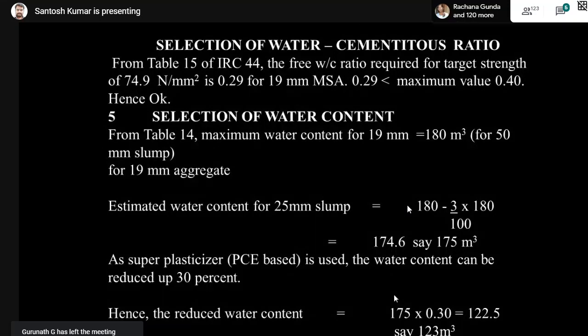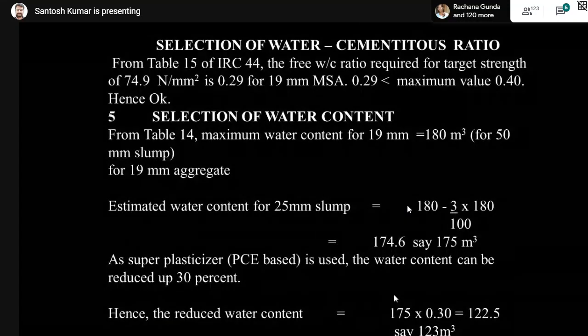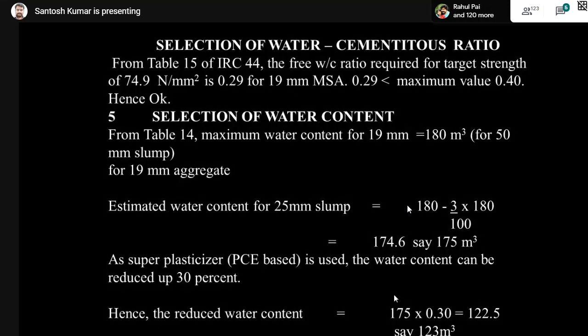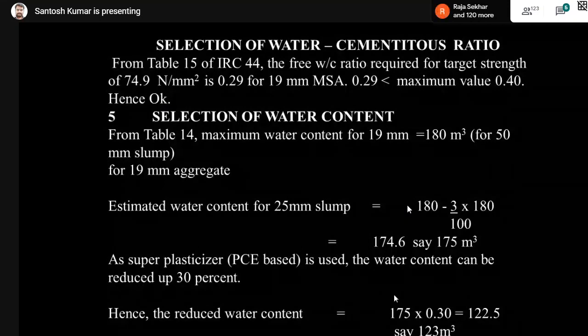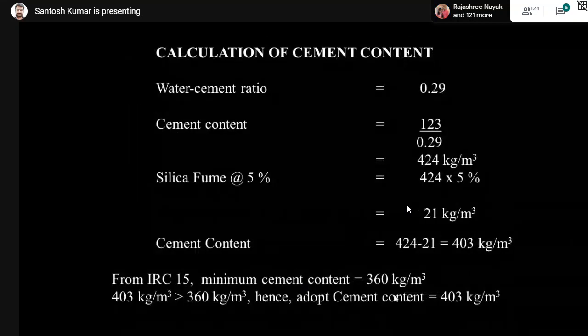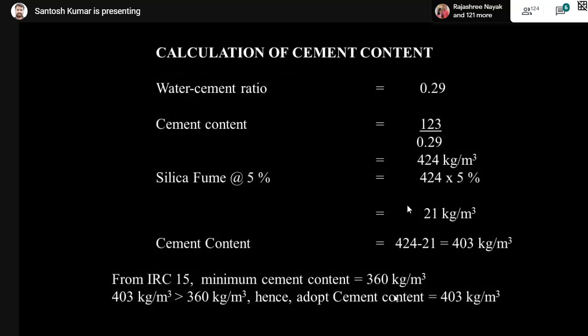So as super plasticizer is used, we are using a polycarboxylate ether based admixture, we can reduce up to 30% of water. So 175 liters, you reduce it by 30%, it becomes 122.5 kg per cubic meter, which is nothing but 123 kg per cubic meter. So the water cement ratio taken in this case is 0.29. Cement content is 123 divided by 0.29. 123 is the water content and 0.29 is the water cement ratio. So water divided by water cement ratio will give you the cement content, which is nothing but 424 kg per cubic meter.